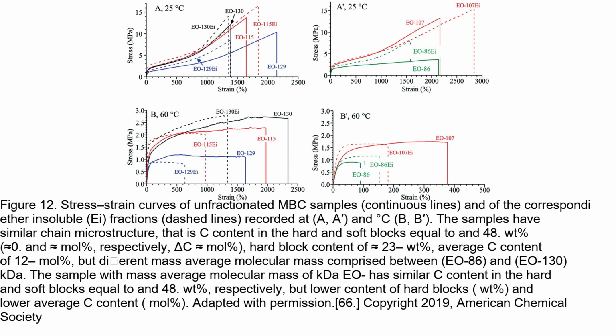Figure 12 shows stress-strain curves for multiblock copolymers, MBCs, with different molecular properties. The MBCs have similar C8 content in the hard and soft blocks but vary in terms of molecular mass and block length. It is observed that MBCs with higher molecular mass and more blocks exhibit greater mechanical resistance and higher